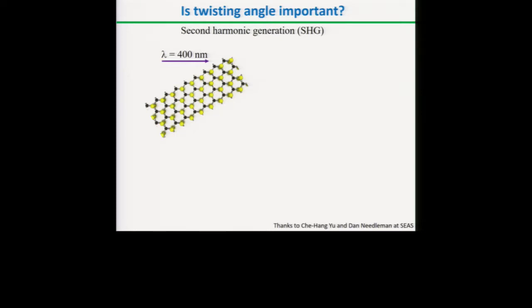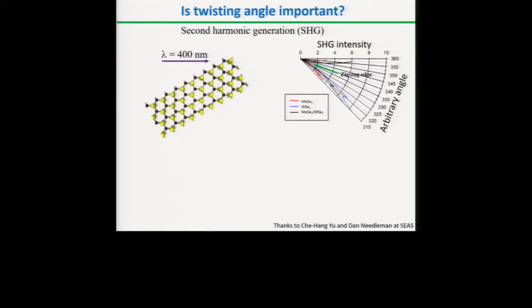By keeping the polarization of the laser fixed and rotating the sample, we can find out where the zigzag edge is for each of these individual materials. And that's what we did here. We did it on the MoSe2, on the tungsten selenide, and on the heterostructure. And they are all aligned. They all have a minimum near this arbitrary angle, with respect to the fixed laser polarization.